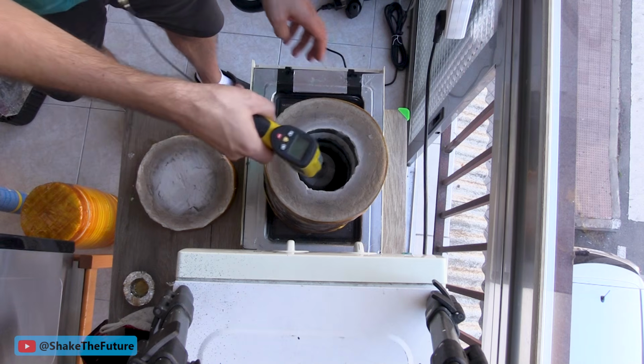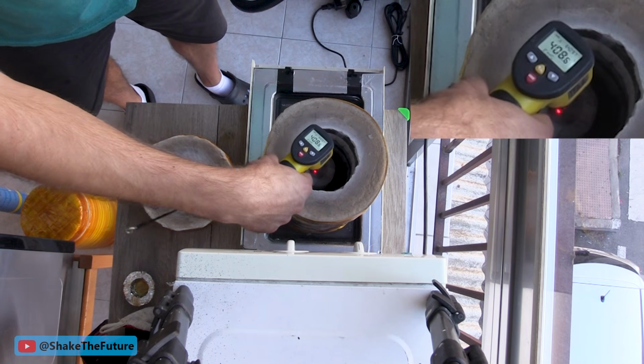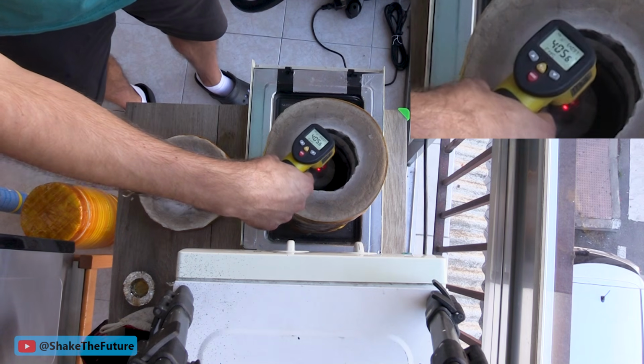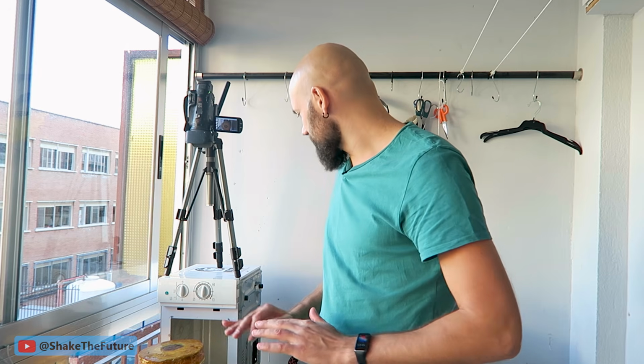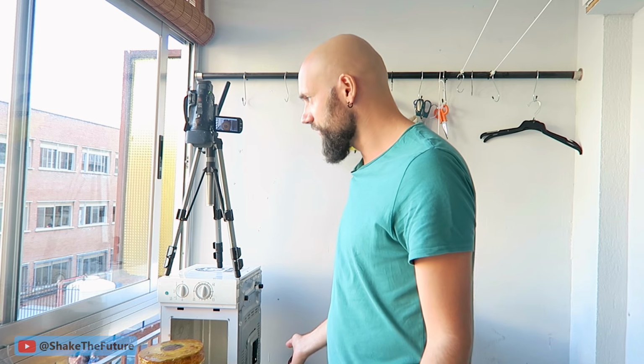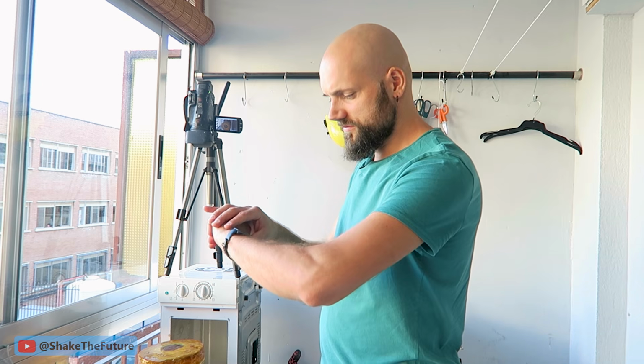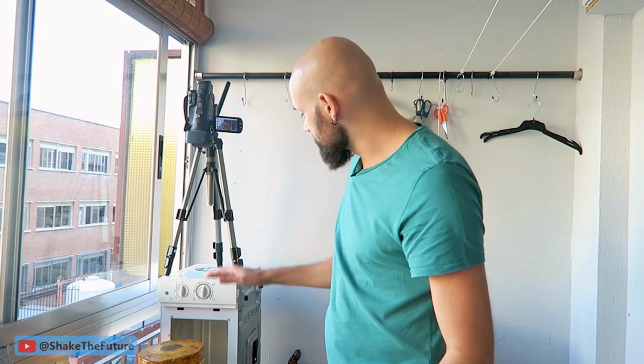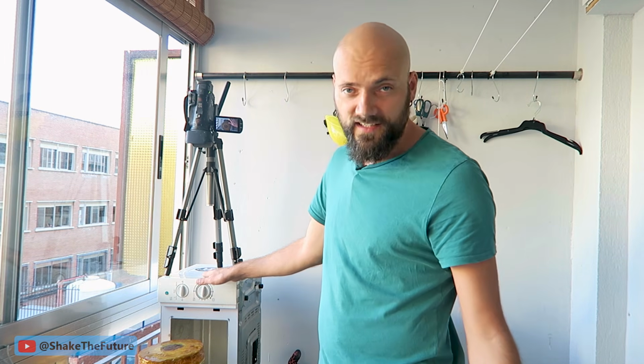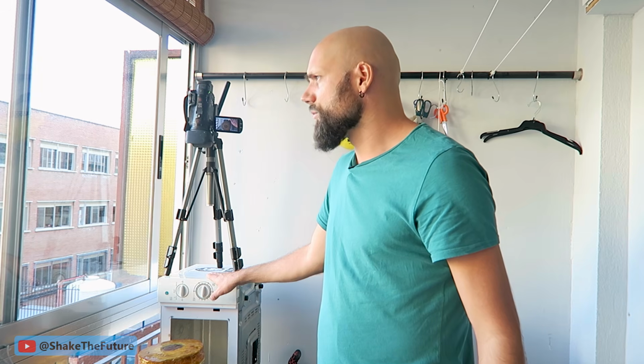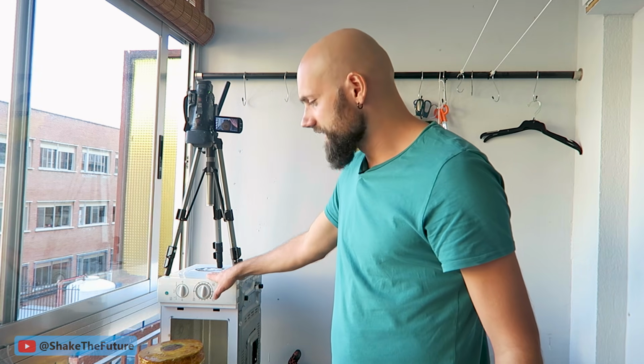The mold has been burned out. According to this, it's 400 degrees Celsius on the top. At this point, I have not done anything - the microwave has burned out the mold automatically. The cycle was 1 minute on, 6 minutes off, and as you see, in 4 hours and 20 minutes since it turned on, the mold has been burned out. The only thing I did was remove the foil and flip the mold upside down.